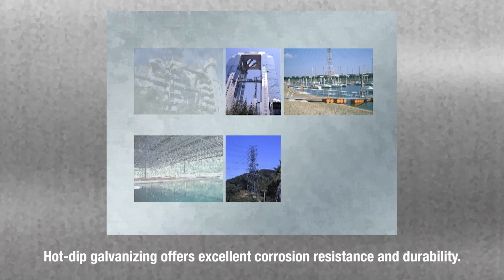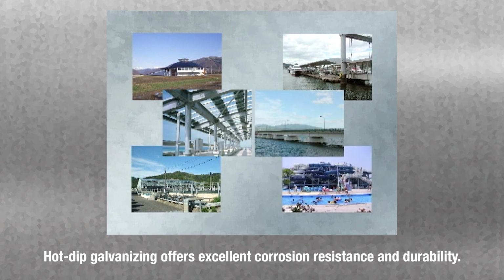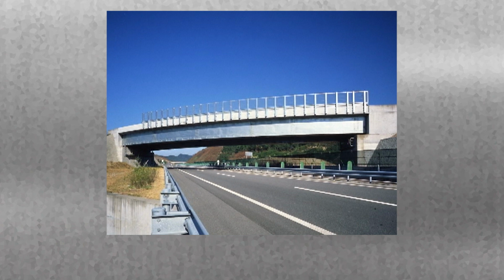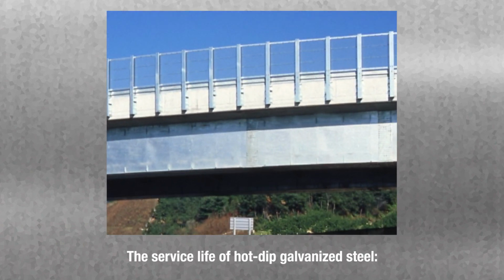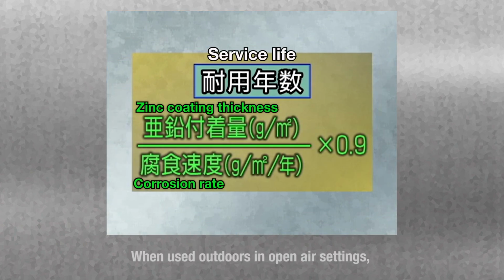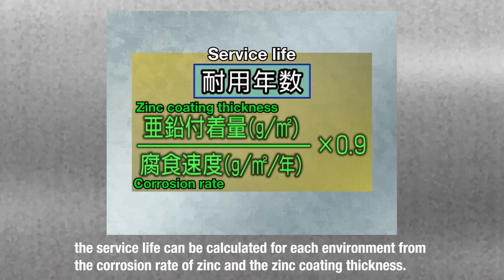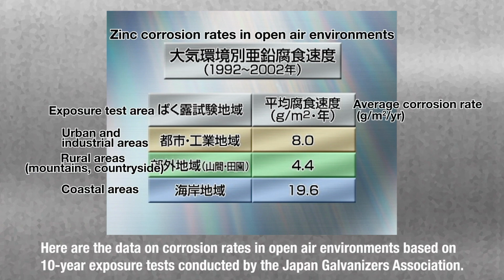Hot-dip galvanizing offers excellent corrosion resistance and durability. The service life of hot-dip galvanized steel. When used outdoors in open-air settings, the service life can be calculated for each environment from the corrosion rate of zinc and the zinc coating thickness. Here are the data on corrosion rates in open-air environments based on 10-year exposure tests conducted by the Japan Galvanizers Association.